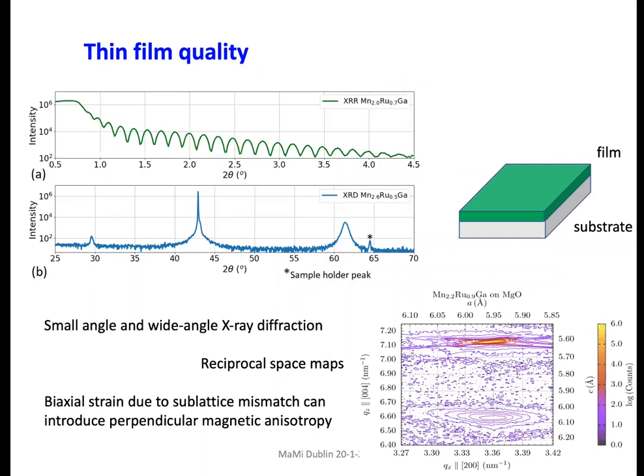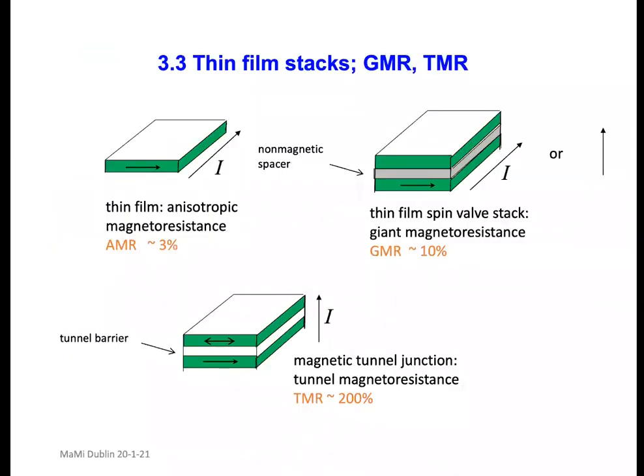The film quality was excellent. We see these interference fringes at low angles. We see reciprocal space maps to see how the film grows on a substrate. And then not only can we make single films, for example, of permalloy, which has anisotropic magnetoresistance, but spin valves, which are stacks with artificial constructs, where we have sandwiches of two different magnetic layers separated by copper. Now, if one's pinned and the direction of magnetization of the other one changes, we can get a giant magnetoresistance,